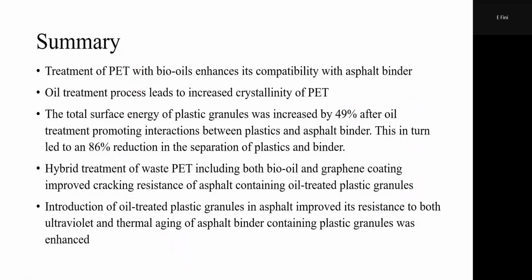So in summary, I want to tell you that when you actually use a new material, a recycled material, whether it's plastic like we just talked about, or any other so-called waste, you need to figure out if they are compatible. That's the very first step. And then if it's not compatible, the second question is, can it be compatibilized? Can it be made compatible by doing something to it? So in this case, treatment of plastic, in this case polyethylene terephthalate, PET, actually improved compatibility. And we have a Raman test showing we increased crystallinity. The surface energy was increased by 49%. In addition to that, we had a significant reduction in separation, which proves that they like each other more.